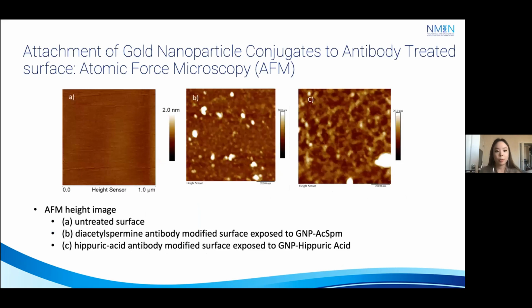And then we also performed AFM on our gold nanoparticle acetylspermine, as well as gold nanoparticle hippuric acid conjugates, again showing this greater incidence of these 20 nanometer particles, which corresponds to the size of these conjugates, suggesting that we were able to successfully bind these conjugates onto the surface of the electrode.